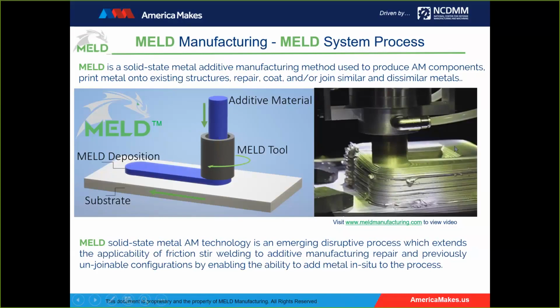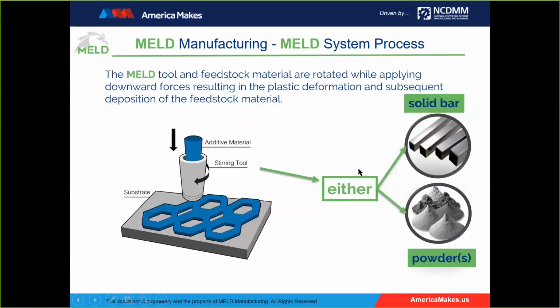Now we're making a rectangular platform, but now through RPMs and linear forces, we're able to heat that material via friction forces up to about 80% of its solidus point, and then we begin to print the metal. So we don't melt it. That's the key to our technology. We don't melt it, and therefore it's a solid-state technology. And with that, we're able to configure it with a solid bar or a powder.